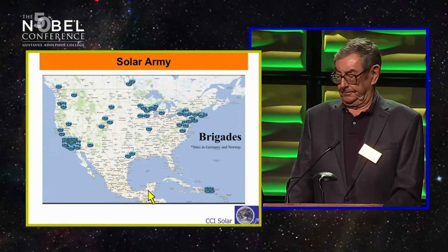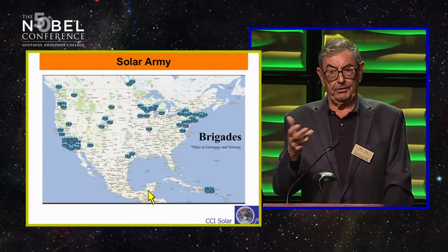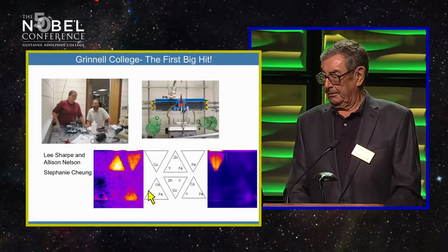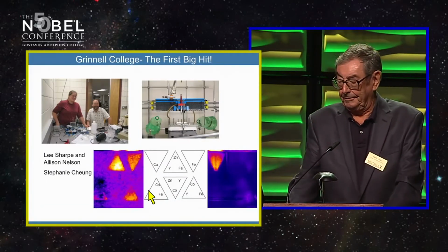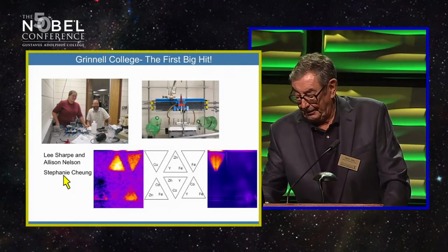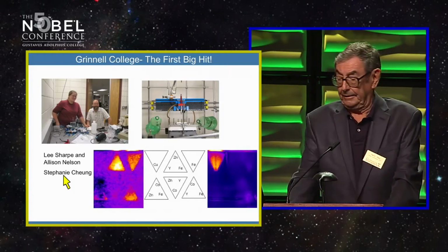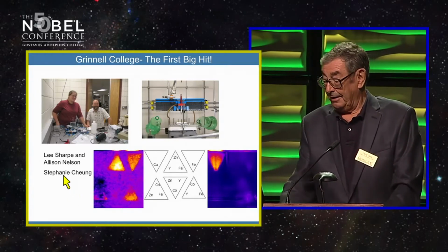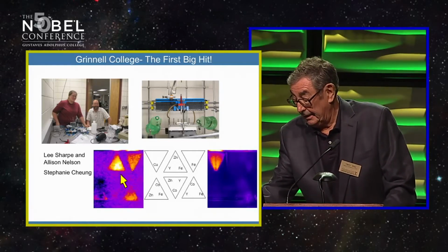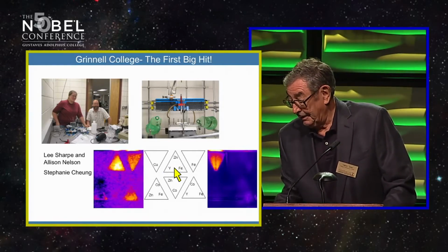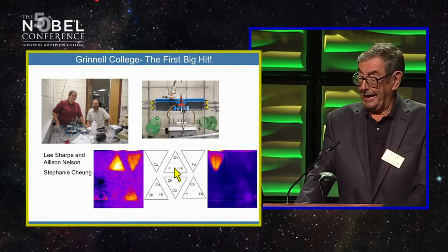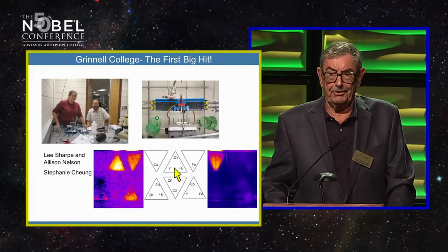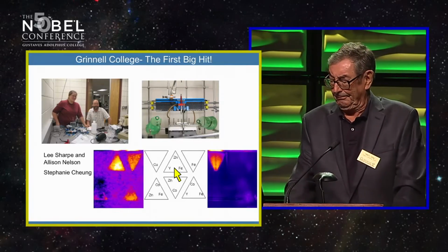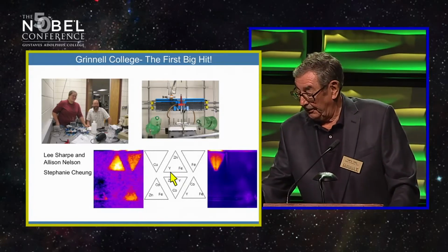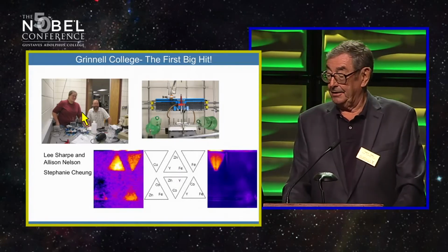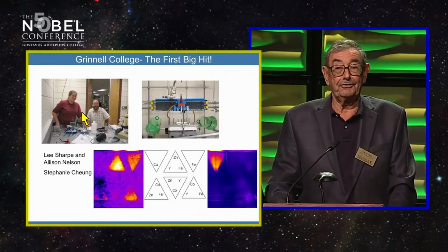What do we do? Well, we search for new materials, and the first big hit was made at Grinnell College in Iowa. A gal by the name of Stephanie Cheung, a junior at Grinnell College, found that if you add the element yttrium to a known zinc-iron catalyst, it gets much, much better for water oxidation, much more efficient. Naturally, the photograph was taken by the 2 professors who left Stephanie out of the picture.